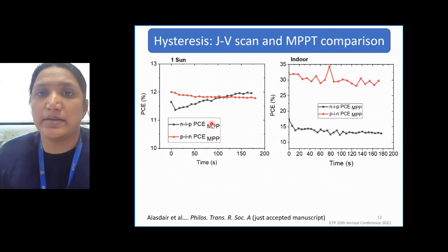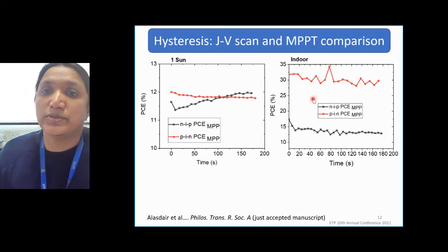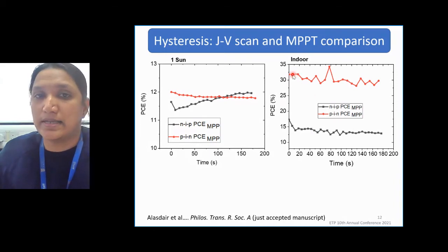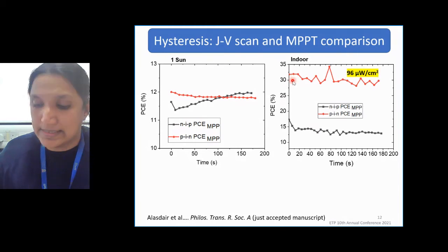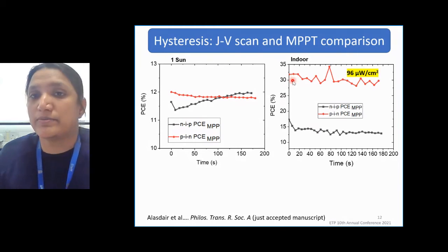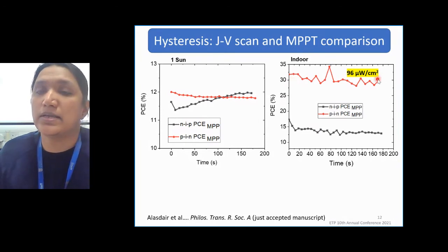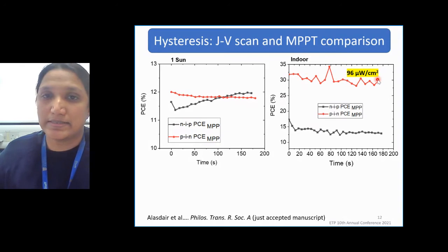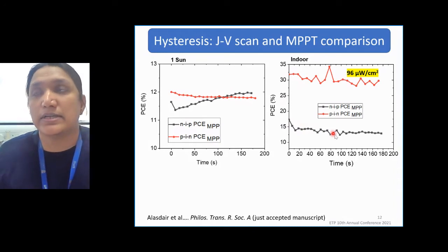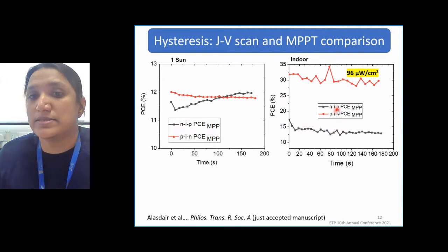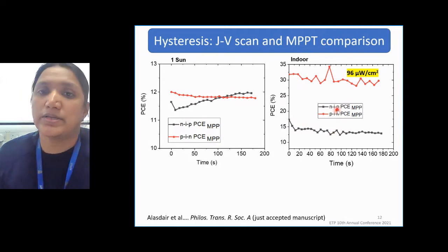And if we consider the similar maximum power point tracking power conversion efficiency in both NIP and PIN devices under indoor light, we can see that again the PIN devices show a consistently high power conversion efficiency above 30%, which corresponds to an output electrical power of 96 microwatt per square centimeter, and it is quite useful to power IoT wireless sensors. Whereas if we look at the NIP devices, the efficiency is only below 15%. When we compare this with the JV curve value under reverse scan, these devices showed an efficiency of 28%, and that was not the actual efficiency of the devices.